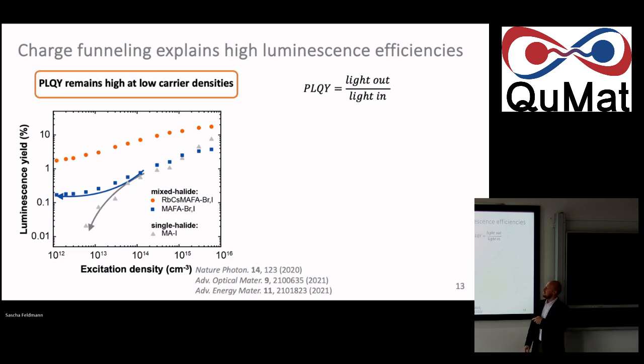And we can see that for the prototype single halide, one building block only, methyl ammonium iodide, MAPI, in gray, eventually you see the luminescence efficiency drops quite steeply. When you get below a certain excitation density, you might create those electrons and holes, those carriers you want to extract or have recombined in the luminescence experiment. But of course, this material has lots of defects as well, and so they eventually just get stuck and recombine non-radiatively, and you lose your light output. That's bad news, of course, if you want to make use of this excited state that you've created.